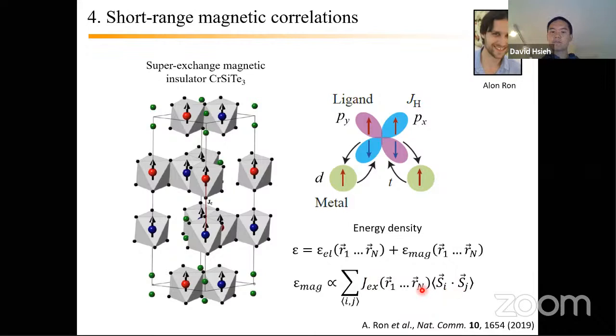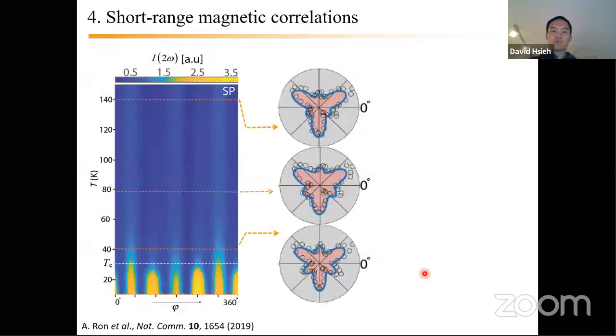And so you can think of this scenario where my spin correlator becomes non-zero. So I haven't ordered yet, but I start developing correlations between neighbors, so the thermal expectation of Si dot Sj becomes non-zero. Then this term becomes operative, and the system, for example the bond angles, can slightly rearrange in order to minimize the energy of this term, right? So your atomic coordinates will respond in such a way as to minimize the total energy, at the expense of maybe some gain in elastic energy if you lose more in the magnetic channel. And so you can actually pick that up in SHG.